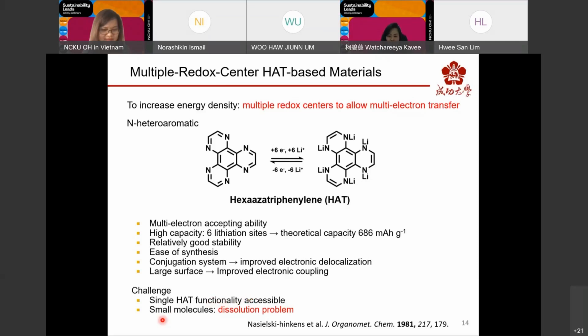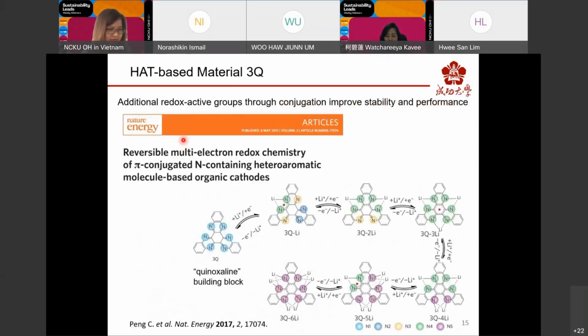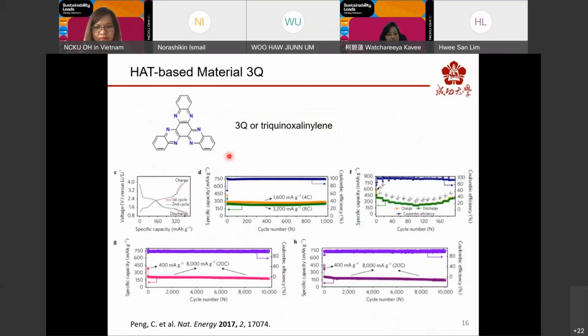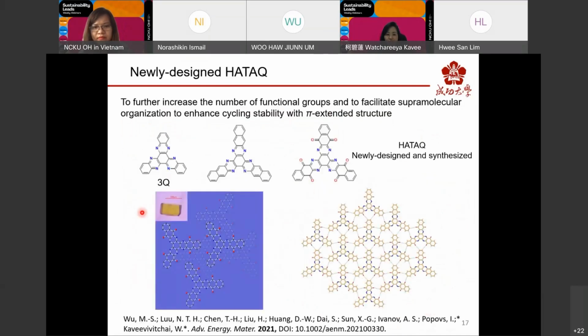And more importantly, small molecule-based materials will usually suffer from dissolution. So potentially, by having an additional redox active group through conjugation to the HAT core, we can improve the structural stability as well as the electrochemical performance. Now, inspired by a work published in Nature Energy, this compound 3Q with HAT core allows 6 electron transfer. The compound 3Q can deliver pretty high capacity as well as good rate performance.